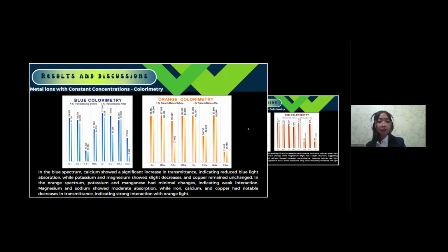The second figure shows orange light transmittance for different materials. Potassium and manganese barely change, meaning weak interaction with orange light. Magnesium and sodium show moderate decreases in transmittance, so they absorb a bit more orange light. Iron and calcium have big drops, absorbing a lot more orange light. Copper also shows a noticeable change, interacting with the orange light too.